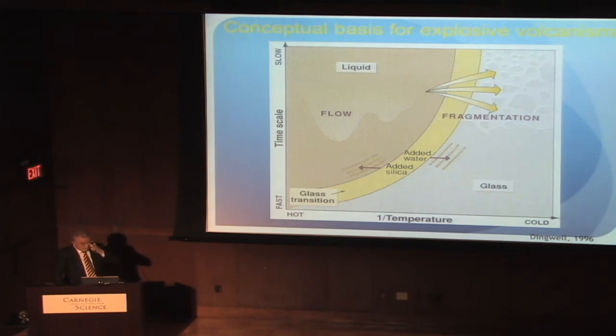Now, when we first proposed this, people said to us, wait a minute, the glass transition here is a low temperature feature. We know they make Coke bottles at the glass transition. Everybody knows that, and they certainly don't go to 1,500 degrees Celsius or 1,200 degrees Celsius to do it. It would cost way too much money. They go to 400, 500, 600 degrees Celsius. The key point of this diagram is that it is time scale on the vertical axis, fast and slow, versus temperature, hot towards me, cold towards the other side, an Arrhenian reciprocal absolute temperature horizontal scale.